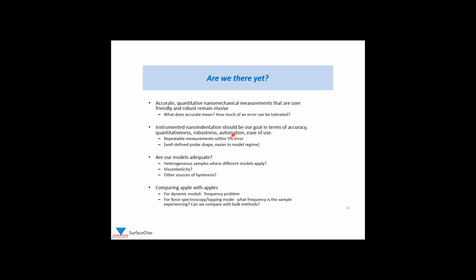Instrumented nanoindentation has repeatability and accuracy within 5%. It does extremely well. Now, there are some real reasons why it does so well compared to, for example, the AFM measurements, including a very well-defined probe shape that is fairly straightforward to calibrate and a regime that's much easier to model. But I still view instrumented nanoindentation as our role model, gold standard, like I said, and we're not there yet.